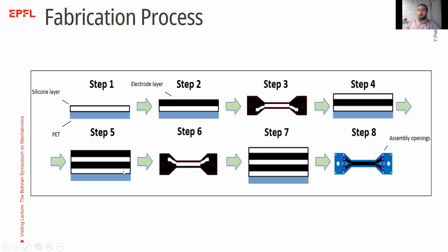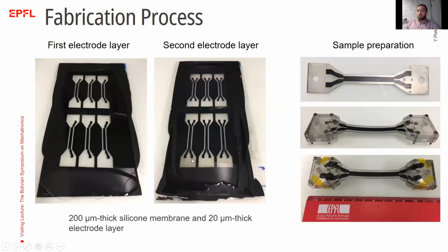You have 3 layers. After that, we put one more silicone layer and etch the electrode, but now on the other side. And then we encapsulate everything in silicone. That's what you see here. That's a sensor that could be used to measure. It is actually a sensor with 2 modes. We have a resistive mode. By connecting to these 2 ends in the bottom and upper part, we can measure the resistance change. But by connecting to 2 ends on one side, we can measure the capacitance change when we're stretching this sensor.